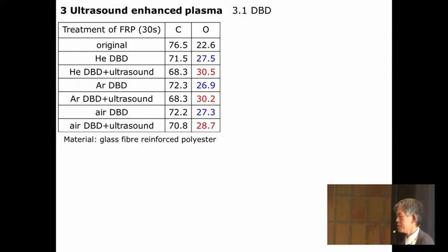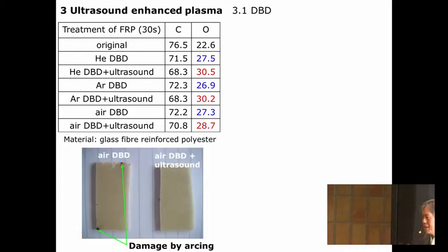Consistently, after the plasma treatment, oxygen content increases. But with ultrasonic irradiation, oxidation is enhanced. But this is as expected. But there are a few unexpected things that make me quite excited. I noticed that the arc can be suppressed if ultrasound is irradiated. In the case of air plasma, we often saw arcing, even though it is DBD, because I try to have relatively high power.